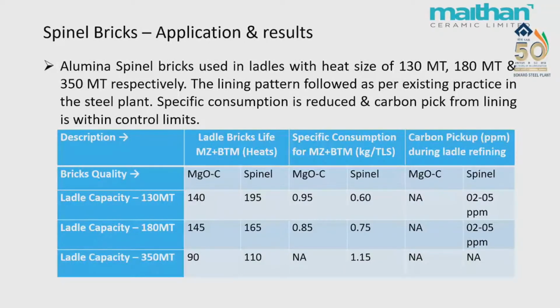130 ton, 180 ton and 350 ton ladles were supplied to Bokaro Steel also. So it will be tried in the month of October. If we see the results for the metal zone and bottom, the performance of the magnesia spinel bricks, we see the difference, the increase in performance, and hence the reduction in specific consumption. And we have very little carbon pickup from the refractories, within the range of 2 to 5 ppm, using the spinel bricks in the metal zone and bottom.